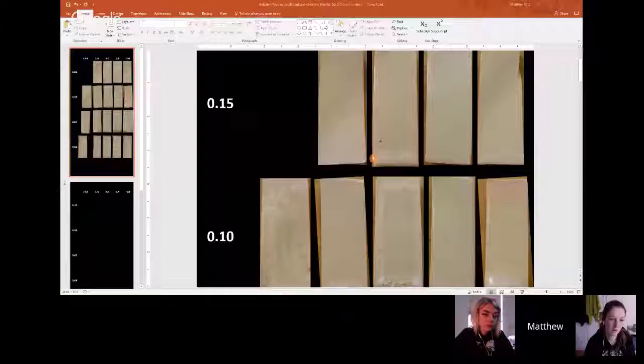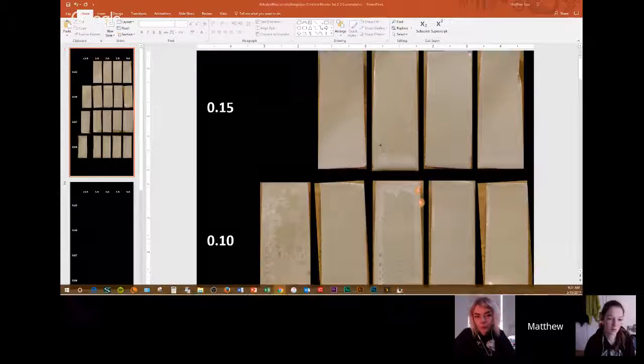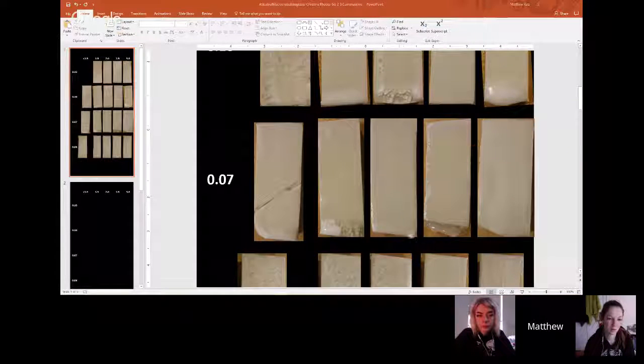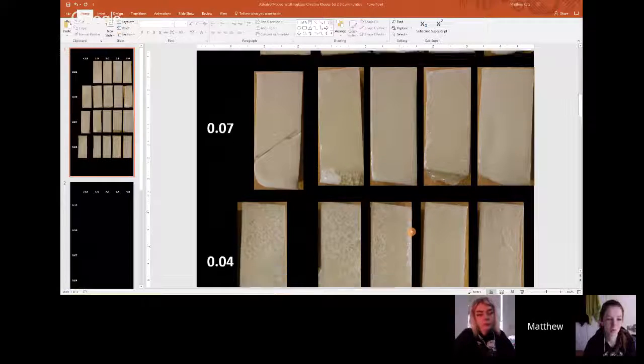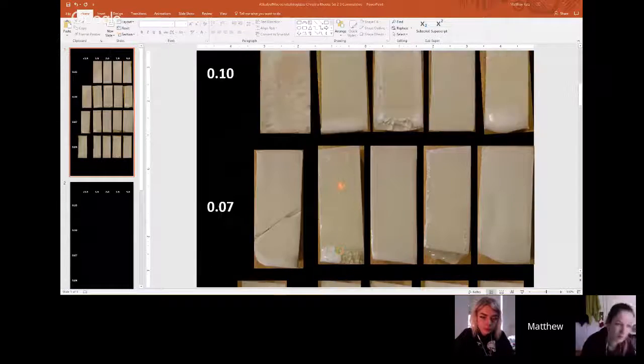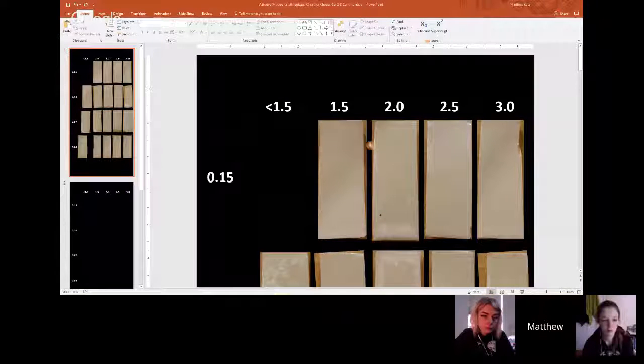So actually I can show this. This was her map without the soak. And you can see that some of them have crystals, some of them don't. But basically, everything came through with crystals with the crystal growth cycle. So it really shows how effective that crystal growth cycle is, and how you're not reliant. Historically you've had to be down in this region, very low alumina. But what we found is crystals here, and we actually have 2 higher alumina levels at 0.2 and 0.25, and there are crystals in all of them. But we'll have to look at that next week. All right. Any other questions for me?